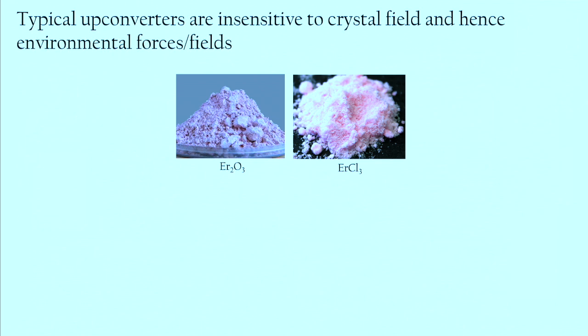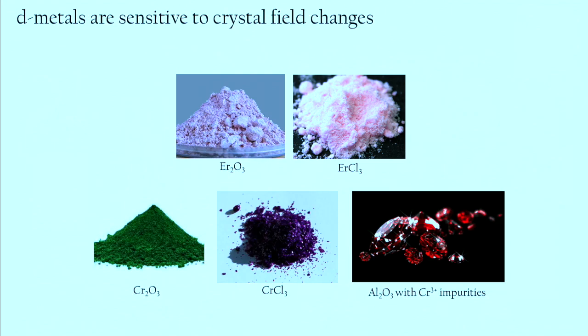But if you go back to your MatSci 202 class, you know that D metals, in contrast, are very sensitive to the surrounding crystal field or ligand field. So D electron orbitals can change their energies in response to, say, an octahedral crystal field or a tetrahedral crystal field, or based on the ligands that are binding to the D metal. So here, for example, are the same oxygen-based and chlorine-based salts that we had, but replacing the erbium now with chromium. And you can see there's a very distinct color change.